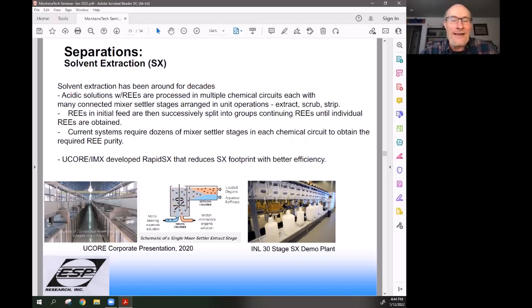And there are probably two buildings the size of football fields on that plant site, with at least 50 to 100 of these massive tanks in each of the buildings. So it gives you a feeling for the scale of the place. It's huge, it's immense, and it smells like kerosene a lot. In order to do these fine splittings of these elements, you have to have dozens of these stages, and you have to have just hundreds of square feet of this material to get it to happen.